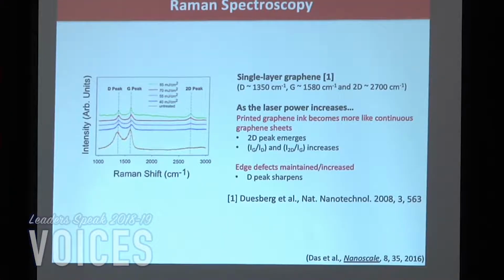If we were to dig down a little deeper and look into the material analysis of what we actually have on that surface, this is just Raman spectroscopy. I won't go too much into that, but we have a D, G and 2D peak. For graphene, you'd expect to see all three of those peaks present. When we don't laser anneal it, we don't have the 2D peak, but when we do laser treat it, we start seeing that 2D peak. So it's becoming more graphene-like, so to speak. And we think that those grain boundaries are starting to stitch or weld together, and it's becoming more of a continuous layer of graphene after we've done this laser treatment.